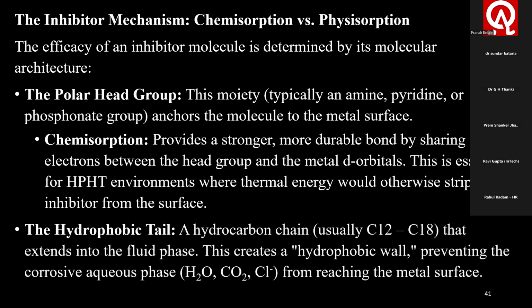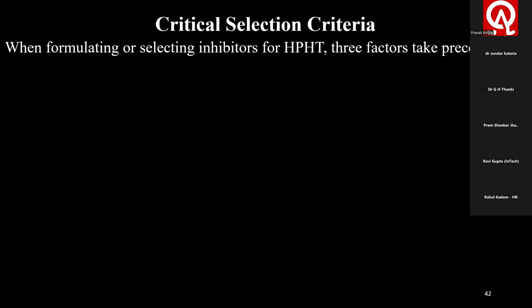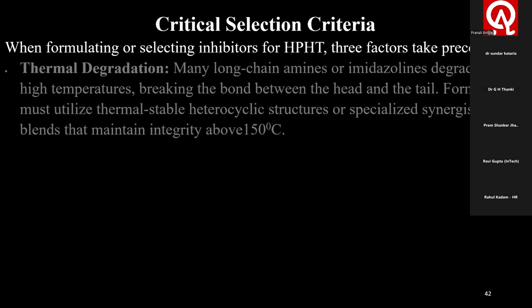The hydrophobic tail, a hydrocarbon chain, usually C12 to C18, extends into the fluid phase. And this creates a hydrophobic wall, preventing the corrosive aqueous phase, H2O, CO2, chloride, from reaching the metal surface. Now, let us see the critical selection criteria. When formulating or selecting inhibitors for HPHT, three factors take precedence.